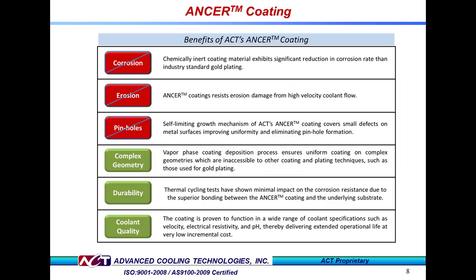The previous slide introduced the ANCER coating. Here is a summary of its benefits. The chemically inert coating has been shown to exhibit a significant reduction in corrosion rate compared to gold plating. We've seen how high velocity coolant flow can produce negative erosive effects. ANCER is a barrier coating that prevents that. The self-limiting deposition process can cover small defects on the surface substrate, producing a pinhole-free coating. The vapor deposition process ensures uniform coating even on complex geometries, which are inaccessible to other liquid coating and plating techniques. The coating is durable.